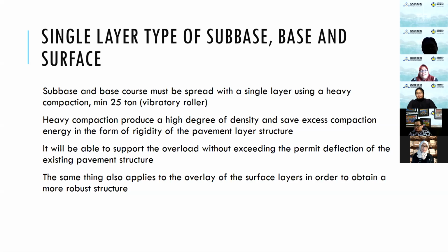But the single layer has more rigidity than the 2 layers with the same thickness. The heavy compaction produces a high degree of density and saves excess compaction energy in the form of rigidity of the pavement layer structure. It will be able to support the overload without exceeding the permitted deflection of the existing pavement surface. The same thing also applies to overlay of the surface layer in order to obtain a stronger structure.